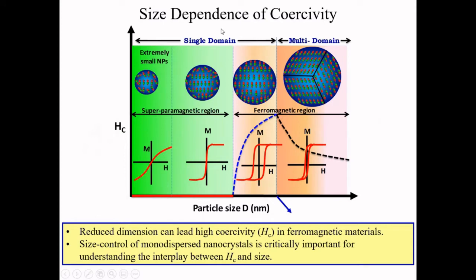Okay, so this is the size dependent coercivity. This slide is saying if we control the particle size of any ferromagnetic material, let's say from a multi-domain structure, which depends mainly on anisotropy, but usually it's above 100 nanometer. So if the size decreases, the coercivity will increase, and exactly at the single domain, we can have high coercivity, because in single domain you can see in this picture, the spins are all aligned in the same direction. So if we apply an external magnetic field, they will coherently rotate. And because of the coherent rotation, they need a high field to reverse completely. In that case, we can have high coercivity.